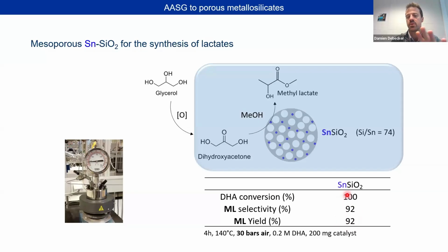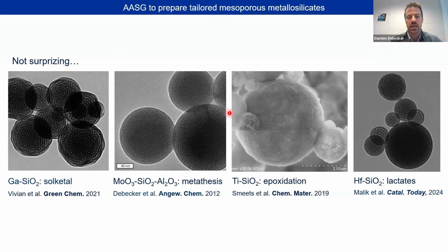So basically, you can remember that that side of the reaction can be completed almost quantitatively, and we have the right catalyst for that, thanks to this high dispersion of the tin. And I would like to tell you that this is actually not really surprising. We have been working on other systems based on gallium, molybdenum, titanium, hafnium for different types of applications, as you can see here. And in all those cases that I show you here, our aerosol-made catalyst showed very high performance.